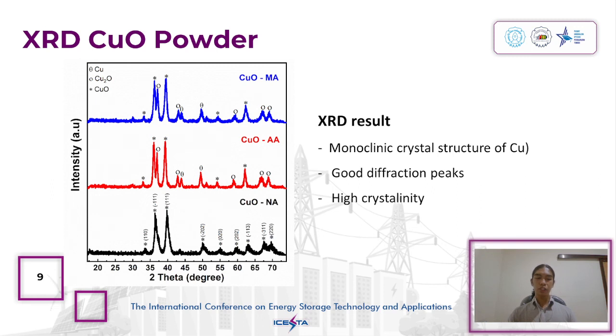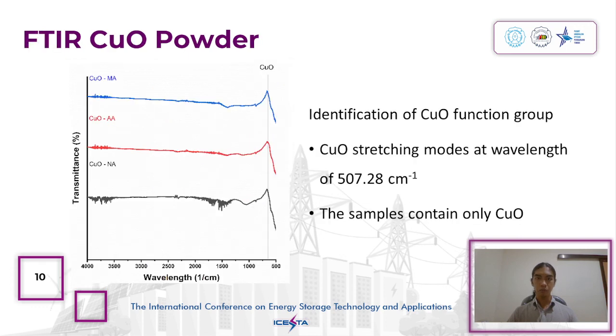Next, the XRD feature for copper oxide powder. For each sample, we can see good characteristic reflection peaks. In addition, the copper oxide sample also demonstrated a monoclinic crystal structure and indicates high crystallinity by sharp peaks. This is the FTIR feature of copper oxide powder.